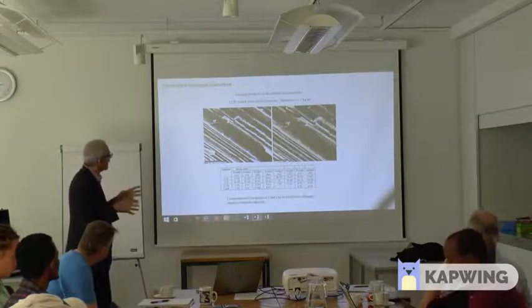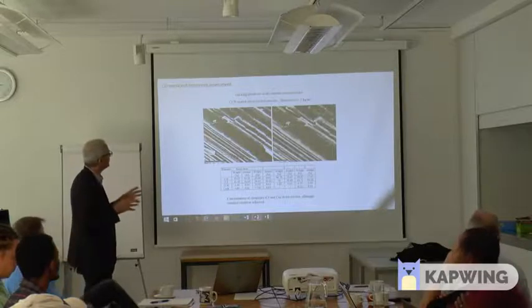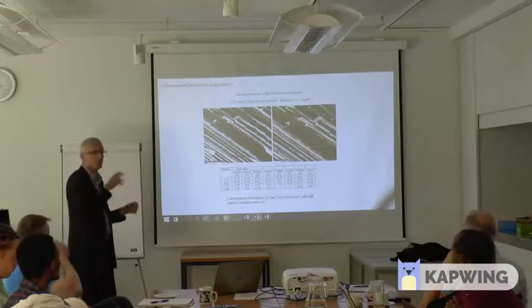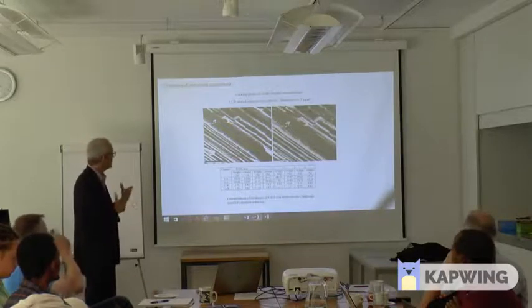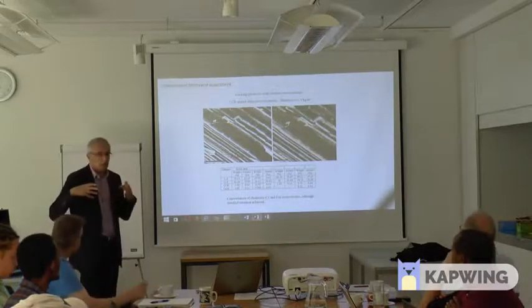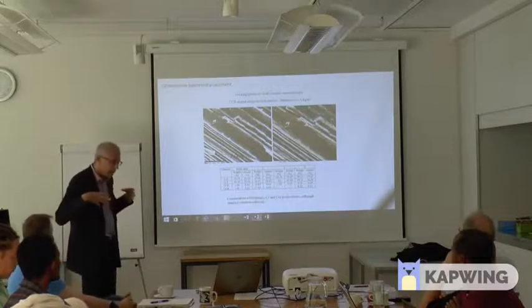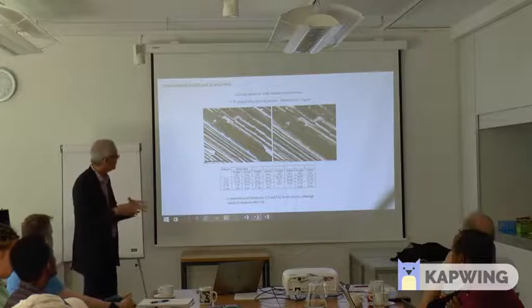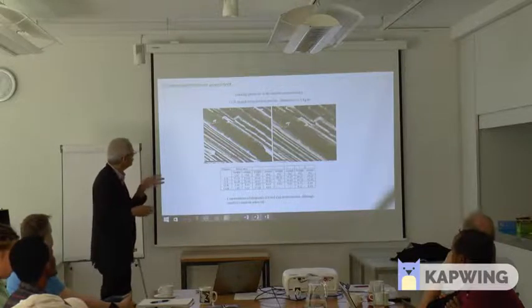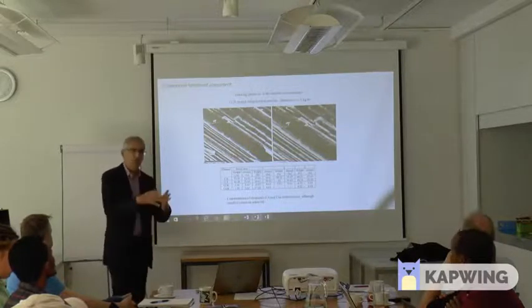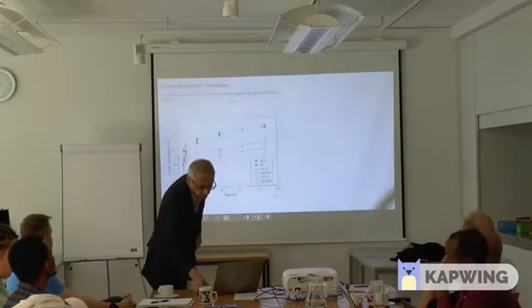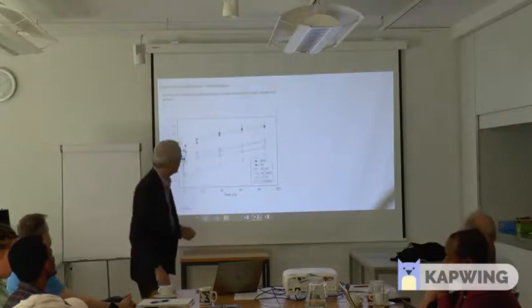So we expect that the treatment goes preferably in this part of the structure of the wood or of the bamboo, and this is nice because in many cases those biological agents that attack the material use those vessels as the routes to invade the structure of the material. So that was the idea.